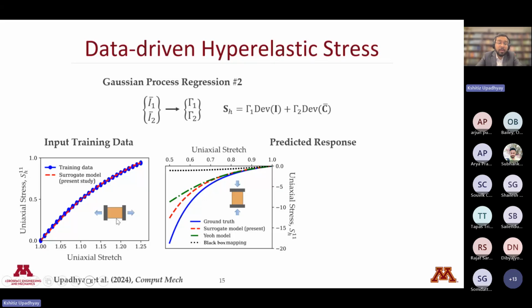It is showing compression-tension asymmetry, which is very commonly seen in soft materials, in that the compression response is much stiffer than the tensile response. When we compare this result with an analytical model, we used the Yeoh model, for example, it also predicts a reasonable response, which is expected from an analytical model, right? But the interesting thing here is that the data-driven model also behaves like an analytical model. At the same time, it brings all the benefits of machine learning methods in that it is automated and fully data-driven.